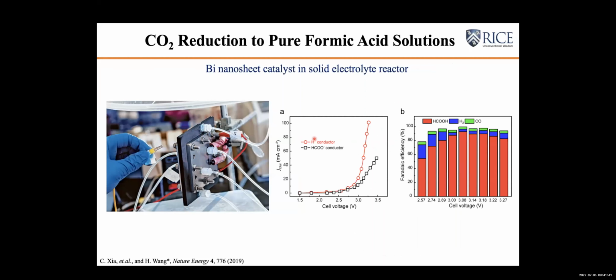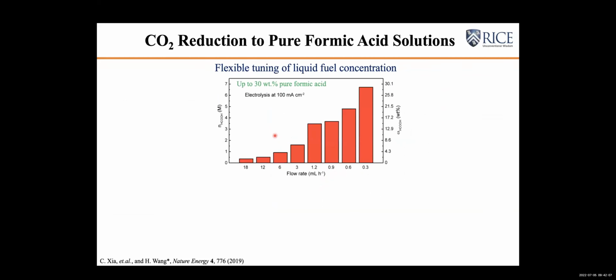As you can see here, depending on the type of solid ion conductor, your IV curve could be slightly different. Of course, protons are easier to conduct, but both of them can reach very high current densities. And the most important thing is, while you're producing this high purity liquid product, you can still maintain a high selectivity of formic acid, over 85% or so.